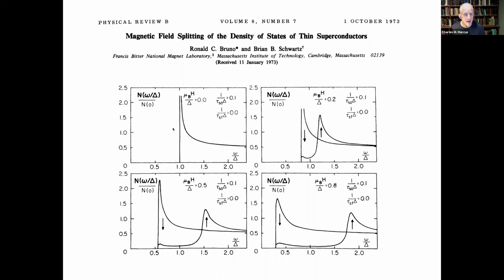And omega in BCS has its peak at 1. Okay, good. So the gap in the density of states is equal to the delta of the order parameter that characterizes superconductivity. This peak is at 1. But as you see, the gap in the density of states in this axis of omega is not 1. One side goes up and one side goes down as you turn on the magnetic field.